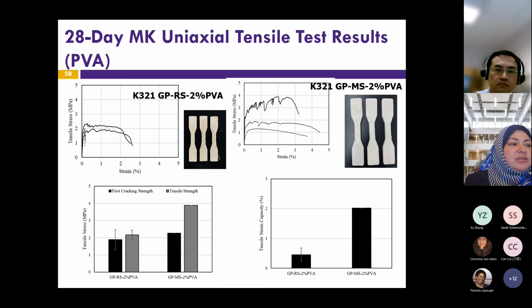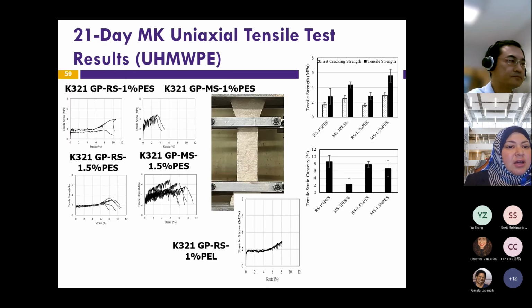Again, a snapshot of the results. This is the 28-day metakaolin uniaxial tensile test. As you can see, all specimens showed a high ductility and pseudo strain hardening behavior. The specimen with the microsilica sand presented the best tensile performance by exhibiting a greater tensile strength and tensile strain capacity. This is the 21-day uniaxial tensile strength for metakaolin with high molecular weight polyethylene fibers instead of the PVA fibers. And again, all of the mixes showed high ductility. The highest tensile strength was achieved with the 1.5% microsilica sand, and the highest tensile strain capacity was achieved with a sample of 1% river sand.